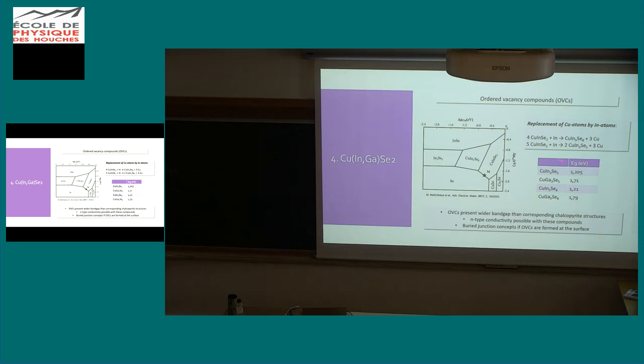And you can form at the same time as chalcopyrite all these compounds that have different band gaps, and also some of them have n-type conductivity. These are called the OVC, ordered vacancy compounds, and are quite specific to chalcopyrite. And I will show you that sometimes they can be even good for the material, not bad.